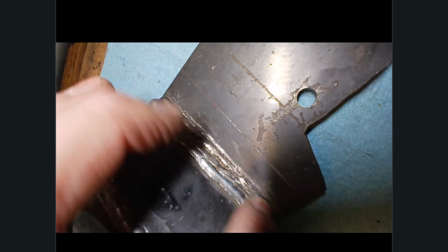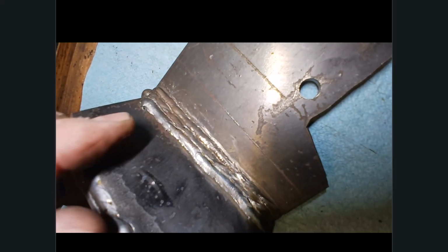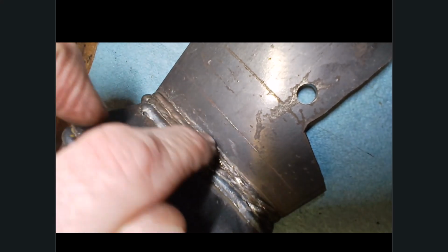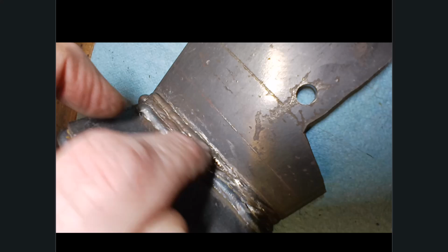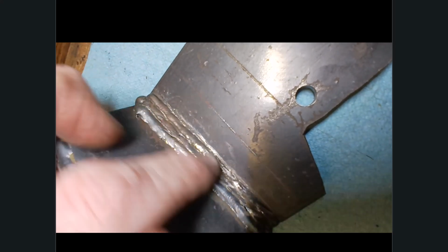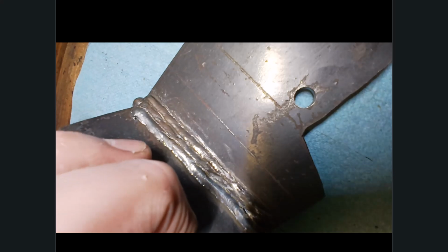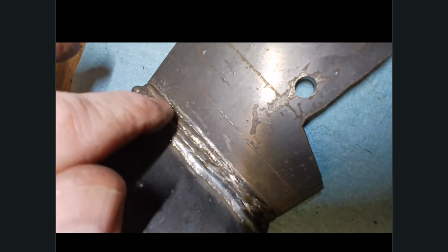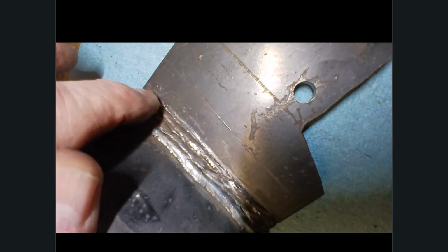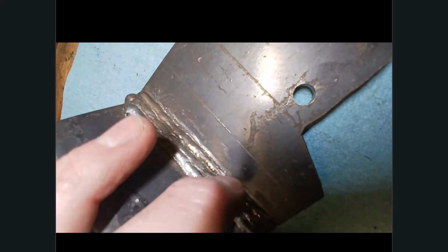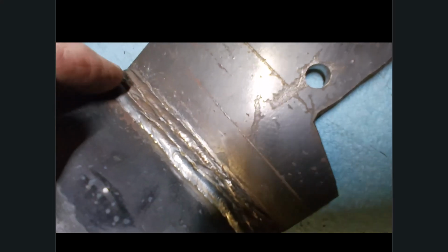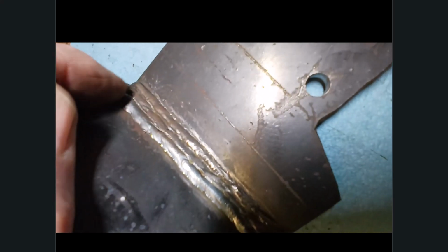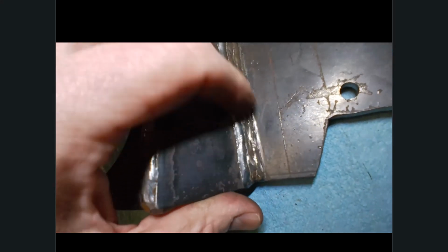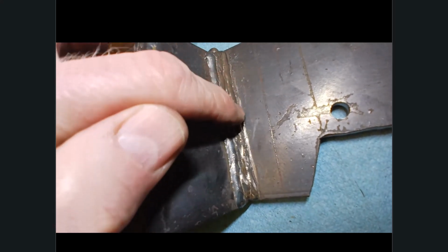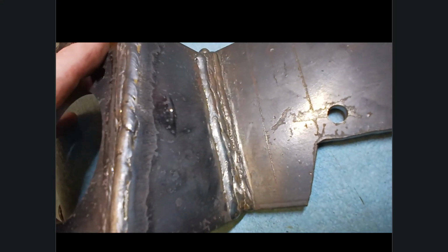I ran a root pass with a 7018 1/8 rod and then 3 stringer beads over that root pass. Every time you run a pass, either the root or the stringer beads above the root pass, you use a wire brush to clean off. So you chip away with your flux hammer and then remove the flux, and then you run past that with a wire brush, a wire wheel, clean it off, and then over your root pass you run 1 stringer bead. And then clean that off, clean the flux off, wire brush it, then run your 2nd stringer bead, and then your 3rd stringer bead, and then finally you're done.